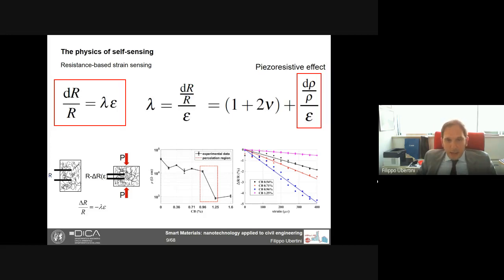So what happens typically in electric resistive strain gauges, for instance, is that this last term is not very important. So typically electric strain gauges have a gauge factor of about 2.1. Where if the Poisson coefficient is something close to 0.5, it means that the last term on the right-hand side of the equation is about 0.1.